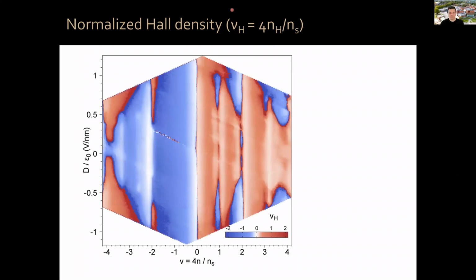And I'm normalizing it by NS and multiplying by 4. I'm dividing essentially by the filling factor, which is the externally induced charge density by the gate voltage. So this is what this normalized Hall density looks like as a function of displacement field and filling factor. And as you can see, it's also a complex phase diagram. Now, most of the features in this phase diagram can be associated with one of 3 characteristics that I'm going to show now.